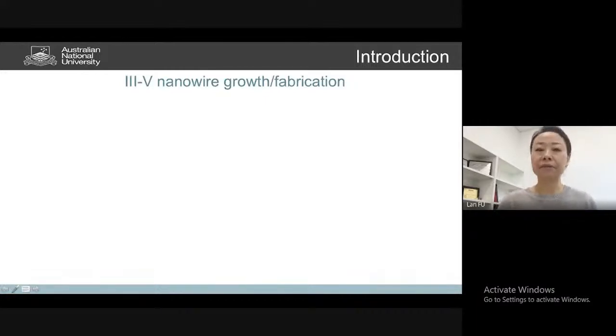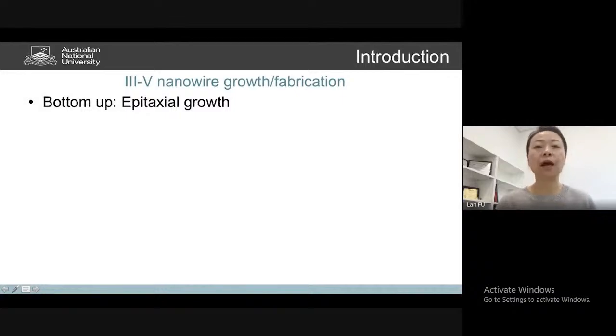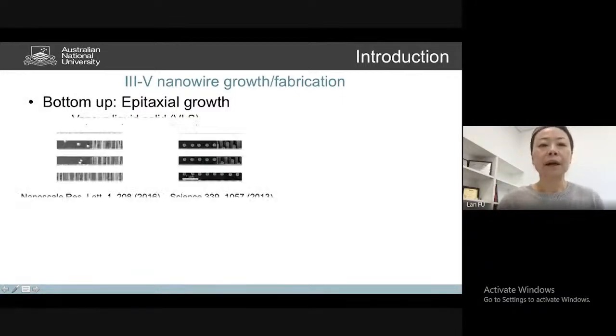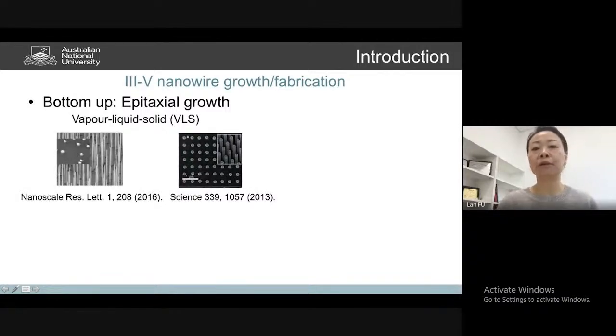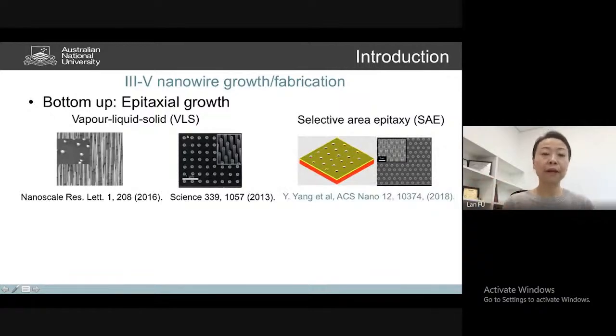So if we look at how we actually make III-V or compound semiconductor nanowires, we use two types of technique. One is called the bottom-up technique, and within it there are two different ways. The first way is using little nanoparticles such as gold. We spray them onto the substrate of your semiconductor. It can be a gallium arsenide or indium phosphide substrate, or even a silicon substrate. That's the earliest study. Using this gold nanoparticle as a little seed to grow nanowires, because it can become a little sink to absorb all the gas-phase precursors, which dissolve into it and promote this one-dimensional growth. You can also use nanolithography to pattern your substrate to make gold nanodiscs and then use those to grow nanowires. Thereby you can grow a very nice and regular array.